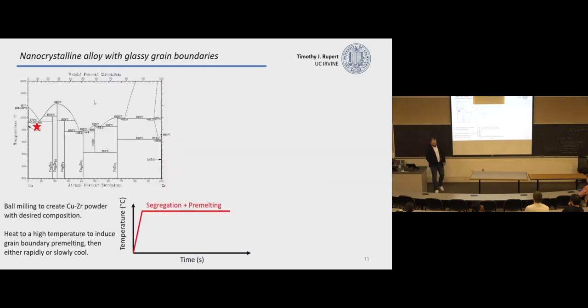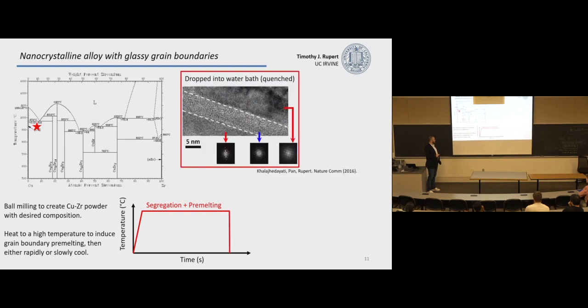Okay, so when we first started working on this, we said we wanted to make a material that could have an amorphous grain boundary. And copper zirconium is the best example of a binary glass former. This is the first material people made into a bulk metallic glass with a simple composition. So what we did is we said, let's take that sample. We're going to choose some composition where we've added enough zirconium that it will need to segregate out to the boundaries. And then we're going to heat it up to very high temperature, but keep it in the range of what should still be a solid on the phase diagram. So when we do this, we get segregation of zirconium to the boundaries, and hopefully we also get a pre-melting type of behavior. So we get that formation of that amorphous complexion. We can test this by quenching down fast and then doing TEM. And sure enough, we find those amorphous grain boundaries in the sample. So here, crystal 1, crystal 2, an amorphous region that is featureless in this FFT.